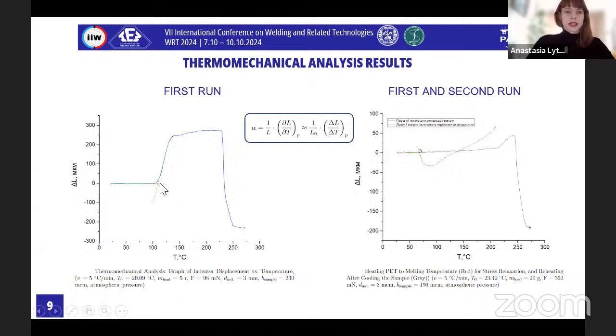We can see here the glass transition temperature, and it can be determined as an intersection of the linear portion of the graph with the sample's expansion and the tangent curve after the onset of expansion. And the temperature of glass transition is 108 degrees, which falls within the values obtained from the DSC analysis results, and it corresponds to the value from other experiments I found when I did my research. So we can see that from the range of 20 to 99 degrees, the sample expansion as a function of temperature is approximately linear. Thus, the coefficients of thermal expansion for unprocessed PET can be determined by using the formula you can see on the screen.